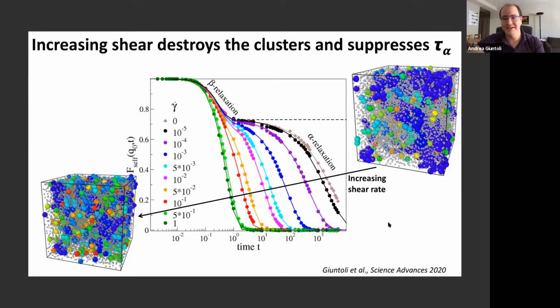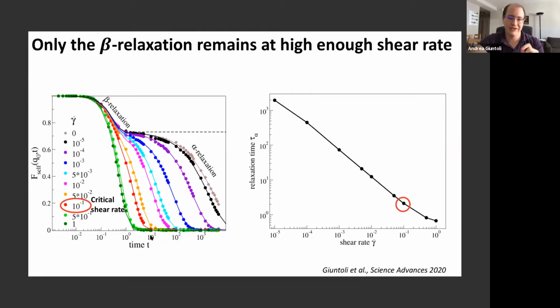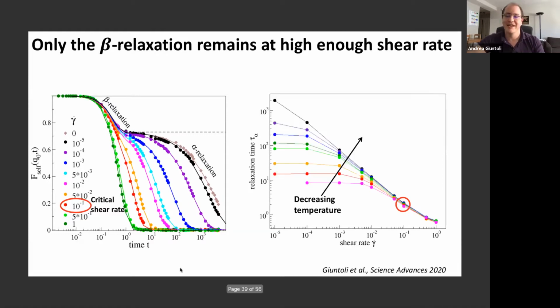So using these ideas, you can measure the alpha relaxation for your systems at different shear rates, and you'll see a plot of the relaxation time as a function of shear rate, similar to that of viscosity. And you can identify some critical shear rate at which the alpha relaxation is gone, and you have a single relaxation here. And you can do that for different temperatures or different conditions in general. And you'll see these different behaviors, the same thing you see for the viscosity of any shear thinning material.